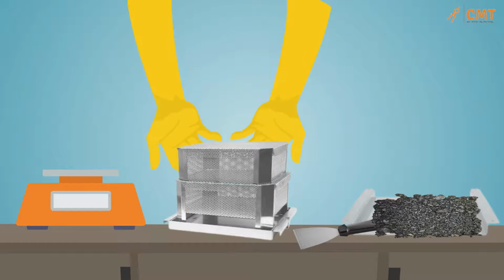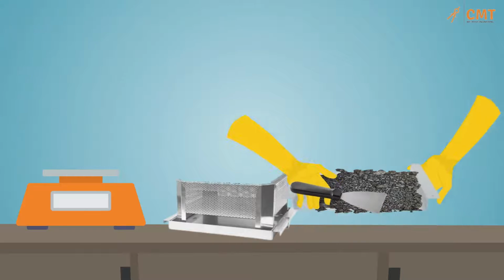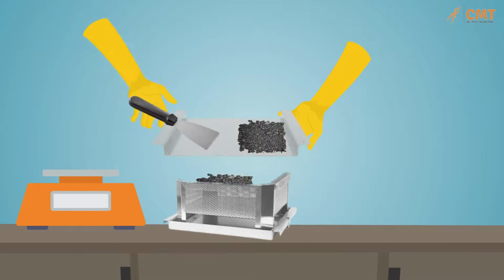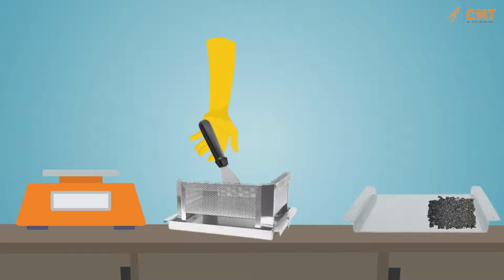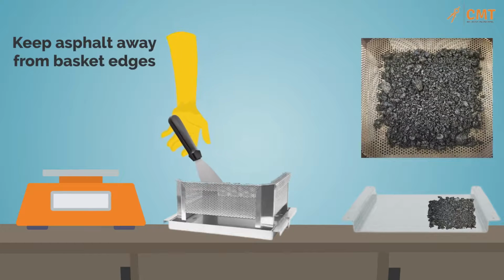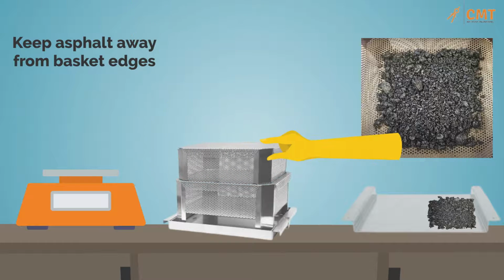Next, you will remove the top basket and set it aside. Then place approximately half of the sample in the bottom basket. Make sure the sample is evenly distributed in the basket and move the mix away from the basket edges to prevent material loss during testing. Then you will replace the top basket and remove the lid.